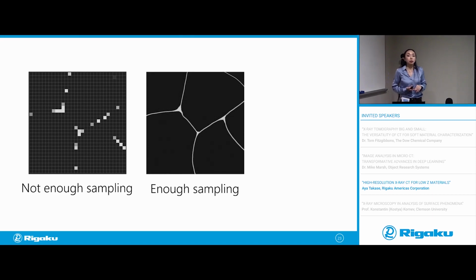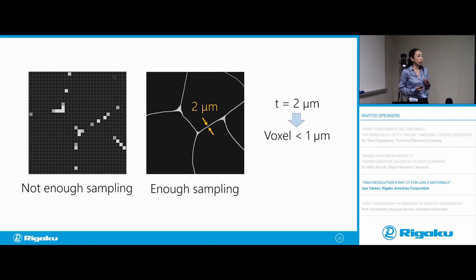And the way to tell what would be enough is to think about the smallest feature you're trying to measure. In this case, let's say that whatever fiber or wall is 2 microns thick. If the smallest feature you're trying to image is 2 microns, your sampling size needs to be at least half of it. You can easily tell if it's more than 2 microns, you're not going to be able to see that line. But ideally, you want to have it about a quarter, maybe even smaller, but at least it needs to be half of the feature size you're trying to see.